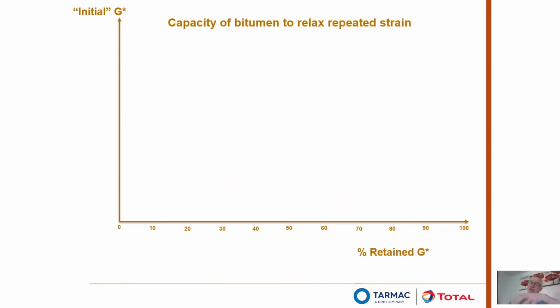So the vertical axis here is measuring the complex modulus, or the stiffness of the material initially. Because this test is a repeated strain test, as you repeat that strain over several cycles, you start to develop microcracks and the amount of complex modulus drops. And we're measuring here the amount of stiffness that's retained in terms of percent, so percent retained complex modulus after 30 minutes of repeated strain. Okay, so hopefully that'll make sense as we start to look at the graph.